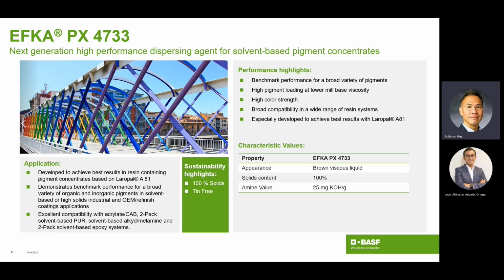So from a sustainability standpoint, this is an excellent product to take a look at. It is very good with all kinds of pigments, to tell you the truth. High performance pigments, which can include organic and inorganic pigments, but it can also do some of your other types of pigments, like even fillers. But this being a more advanced pigment dispersant, I would recommend it more for the high performance category. So this product, EFKA PX 4733, in combination with EFKA FA 4620, are what I would recommend for addressing pigment loading in an epoxy formulation. Excellent, Tony.